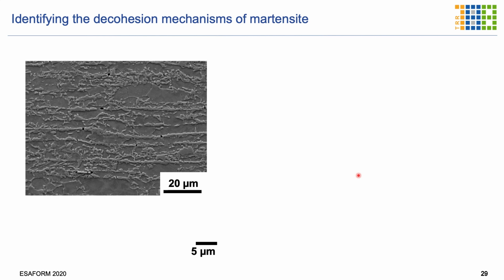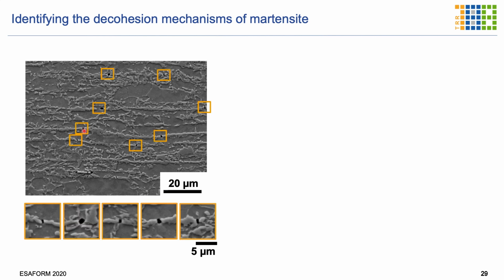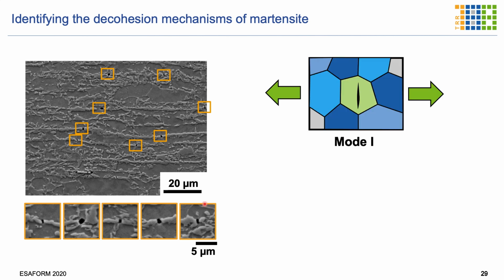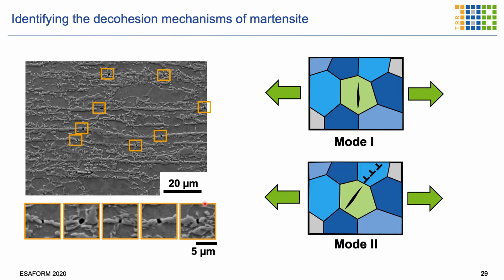So one example is here about the decohesion mechanism of martensite. So how do voids occur? You see here some voids. How do they occur by the decohesion of the martensite from the matrix? So for that purpose, we look at the voids as shown here, different voids, and then analyze how those voids get larger and increase their size. So there are two modes, mode 1 and mode 2. And those two modes are important for our models.